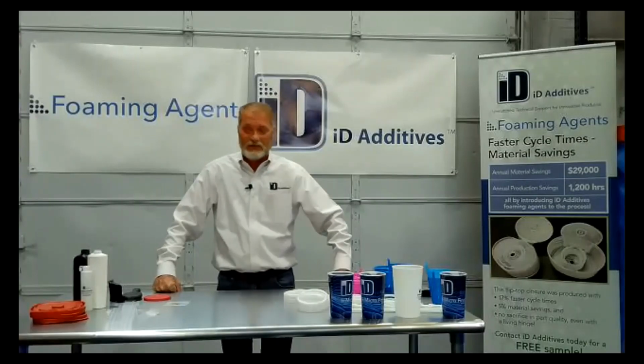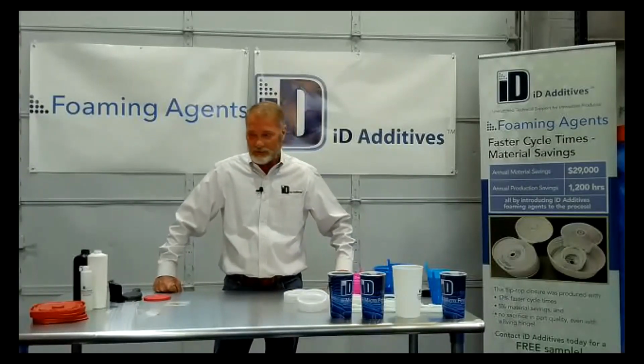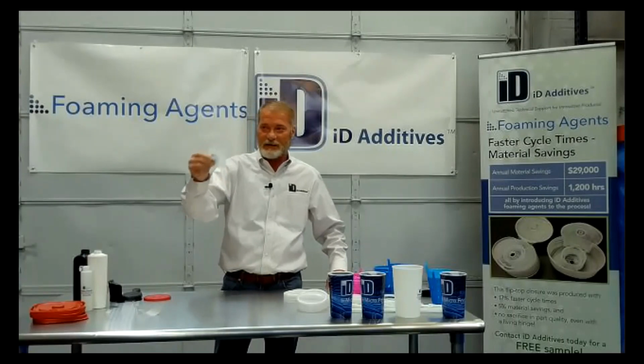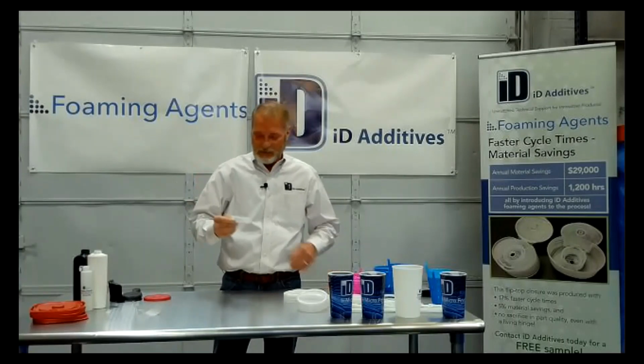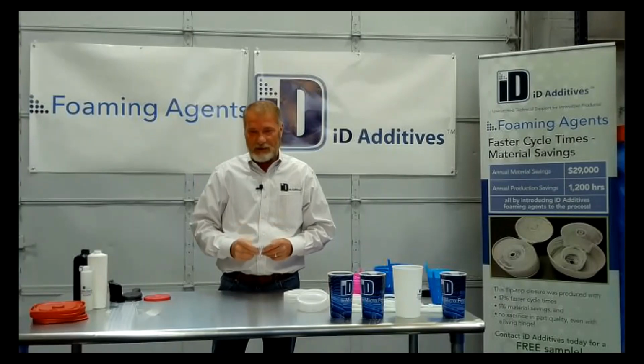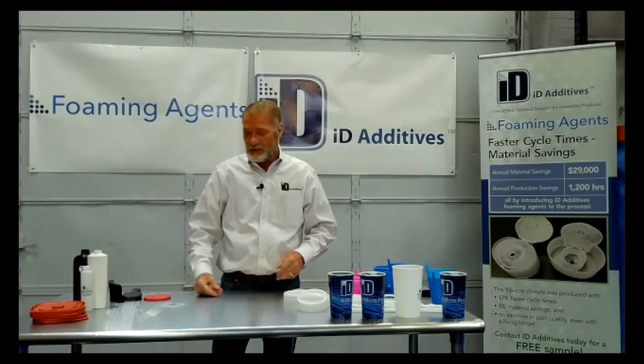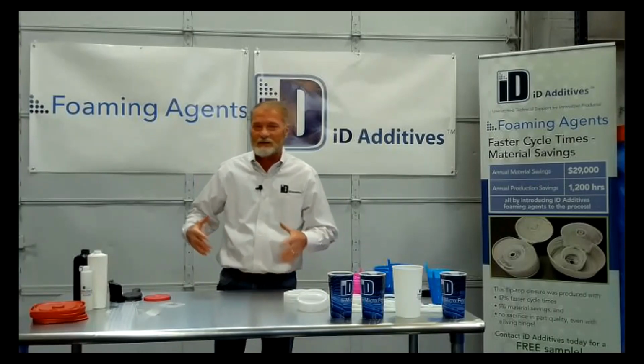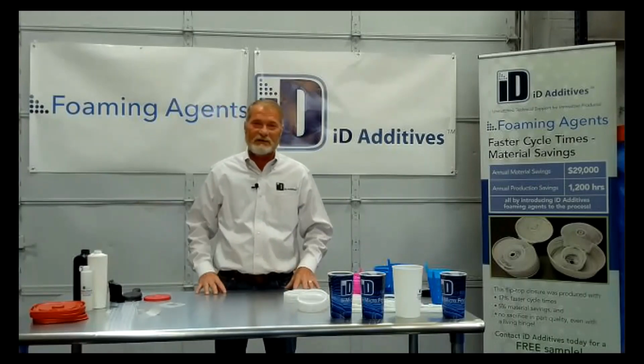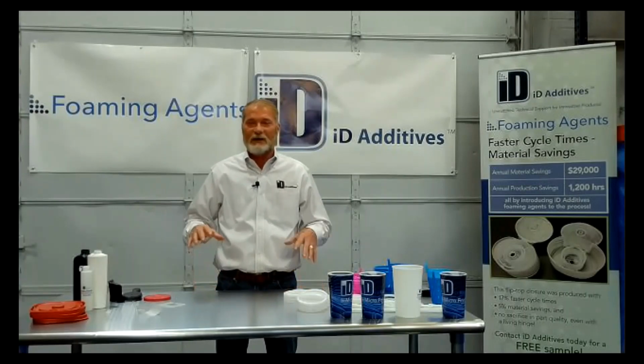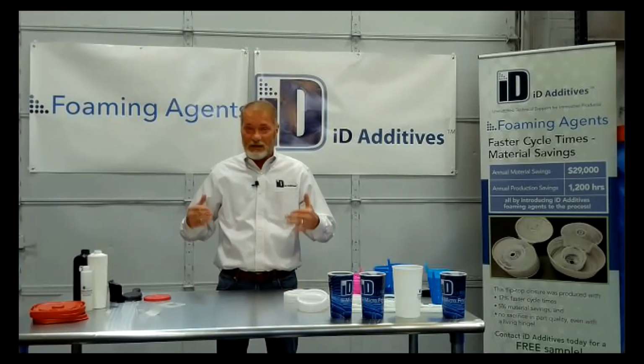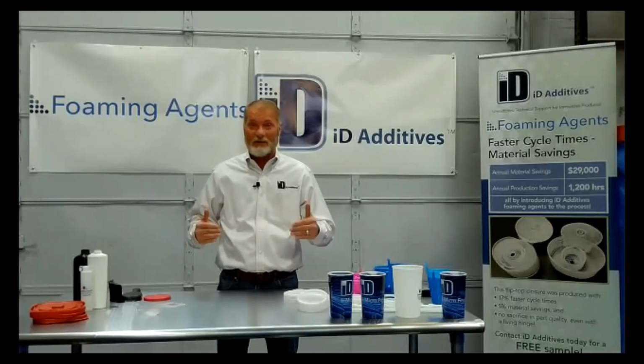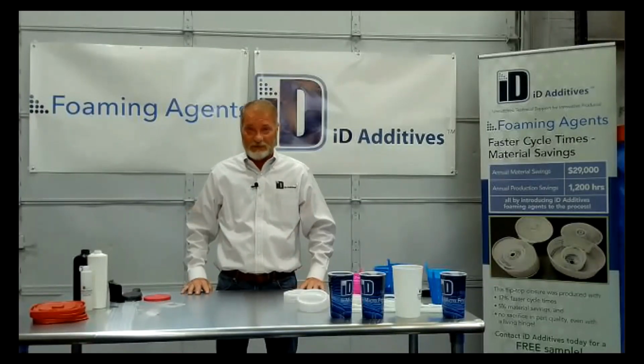I don't know what it was, about 2 mil, maybe 5 mil. It's about that thick of PET. Took about 12% out of it. PET foams really well. It was difficult to talk these guys into dropping those barrel temperatures in PET, because in their minds that just doesn't seem right. But we did drop the barrel temperatures, actually quite a bit, and it foamed beautifully. So I think barrel temperatures is the key to high temperature applications.